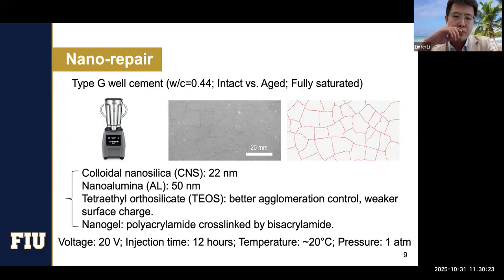We started with lab scale testing. The voltage is about 20 volts. Injection time is exactly as in the RCPT test, 12 hours. Temperature is controlled at room temperature, and there's no extra pressure applied.